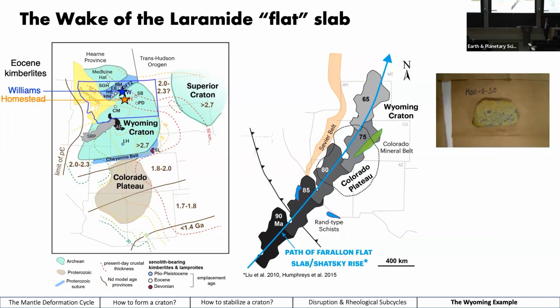We're going to focus on two kimberlite localities: the Williams kimberlite, which erupted closer to the edge of the craton, and the Homestead xenoliths, which erupted a little bit away from the edge. The areas are a little approximate, just to highlight. It's thought that during the late Mesozoic to Cenozoic, we had the impingement of a large oceanic plateau, or some other way we had the Farallon slab becoming much more shallow. That began to plow through southwest Arizona, and this plate reconstruction geodynamic model shows it going all the way to the Wyoming craton by around 65 Ma. And around 55 Ma, during the Eocene, is when these kimberlites erupted.